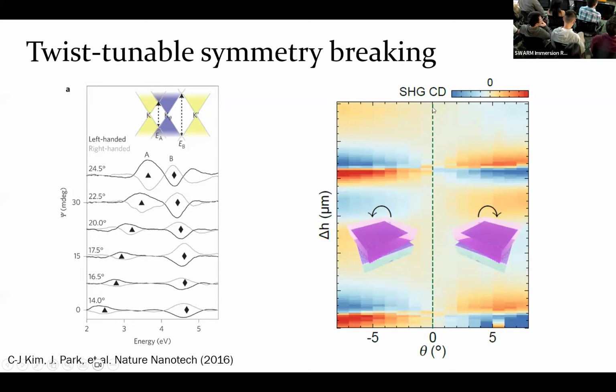So here we're showing in color the circular dichroism of the second harmonic generation. So basically how much second harmonic generation is generated, the difference between the second harmonic generation for left and right-handed circular polarization. And what we're seeing here is that as you change the twist angle, at 0 degrees, it's basically all white, meaning that there is no circular dichroism. But as you twist by a twist angle to the left or to the right, you're seeing opposite signs of the circular dichroism in second harmonic generation. It's perfectly antisymmetric with respect to 0 degrees, just as expected.